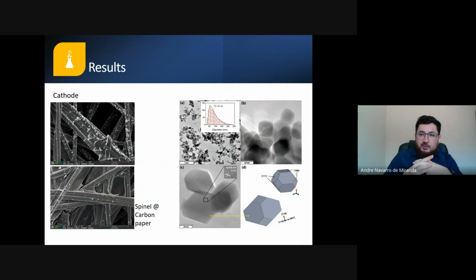So we made a different kind of cathode here, to understand this system, a simpler cathode. It's formed of carbon paper, which is just fibers of carbon, and then we impregnate these carbon fibers with particles of this catalyst. So we did transmission microscopy here to understand this material. And we could see that it has different kinds of shapes, like octahedron shapes. In this shape of particle, we have some surfaces that are exposed to the environment. We could see mainly these two surfaces, 111 and 100.